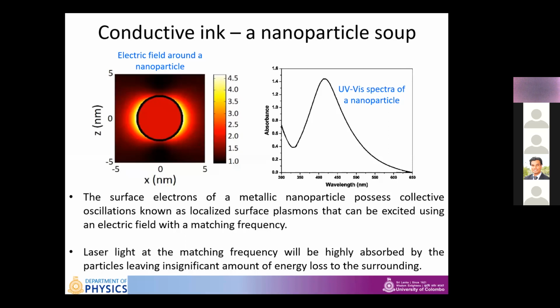The electric field around a 5 nanometer diameter silver nanoparticle dispersed in water and irradiated by a 420 nanometer wavelength laser is shown in the left-hand side picture. That's just a two-dimensional electric field plot. I hope you can easily see that the electric field on the surface of the nanoparticle is enhanced. That is just the bright yellow color. This indicates an effective coupling of the energy of matching frequency light.